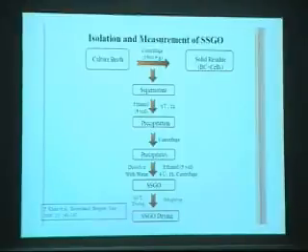They are isolated from the culture broth through the following steps. The culture broth is centrifuged, so the solid material settles down as precipitate, and as these are soluble in water, they remain in the supernatant. Then the supernatant is treated with 5 volumes of ethanol, and with ethanol they are precipitated. The process is repeated 2 times to get a purified form, and finally these are dried to be used in further experiments.